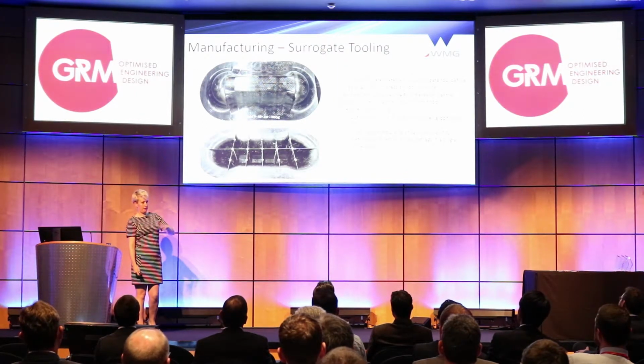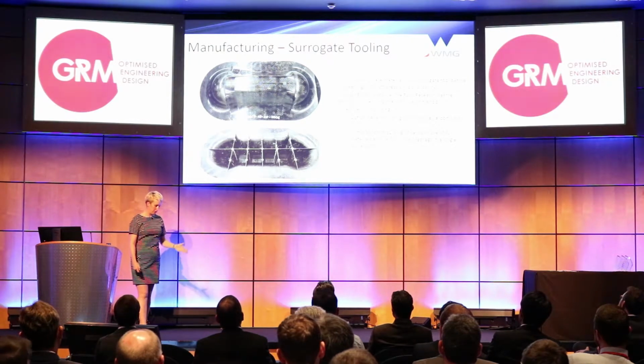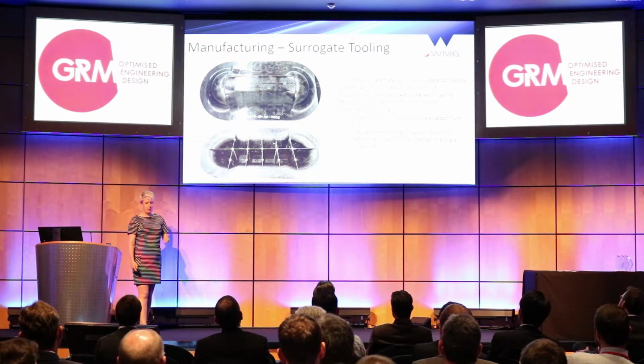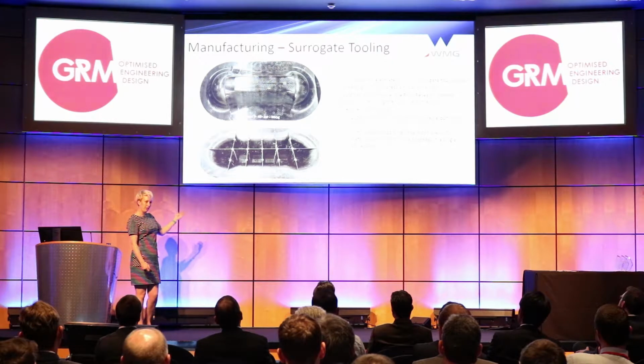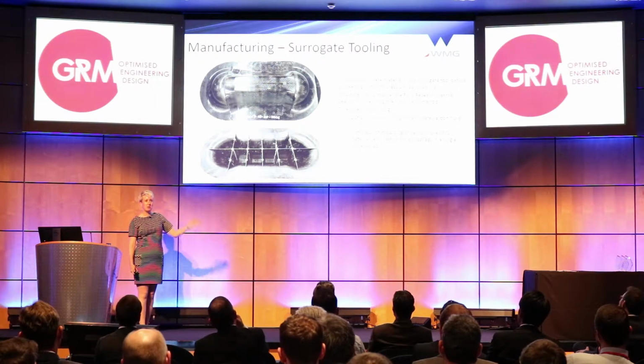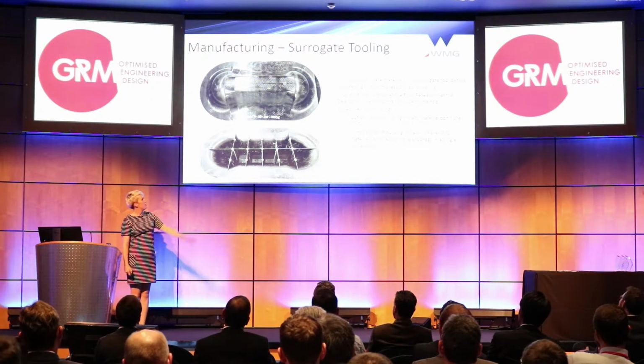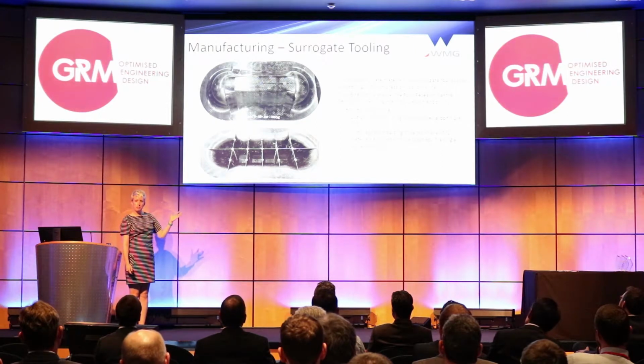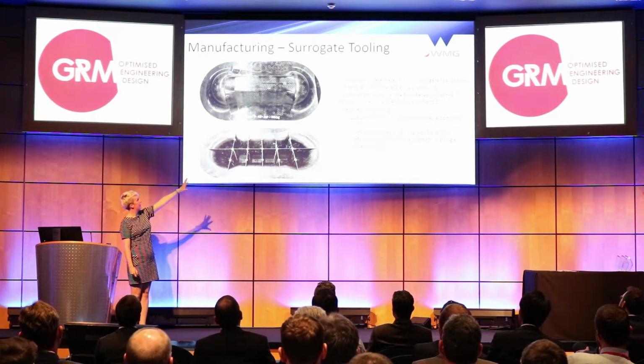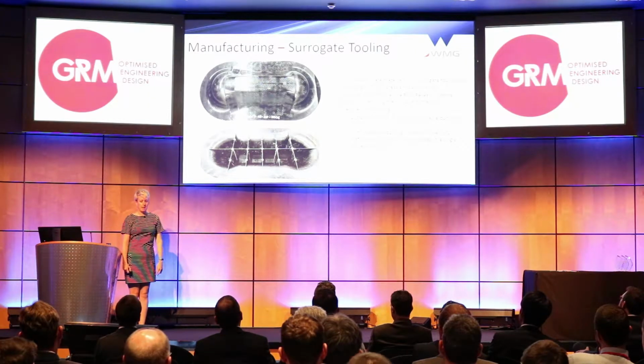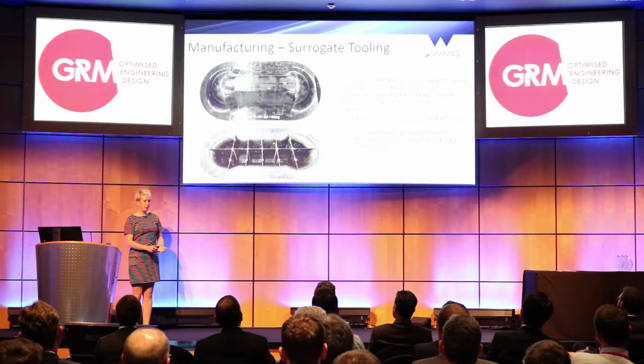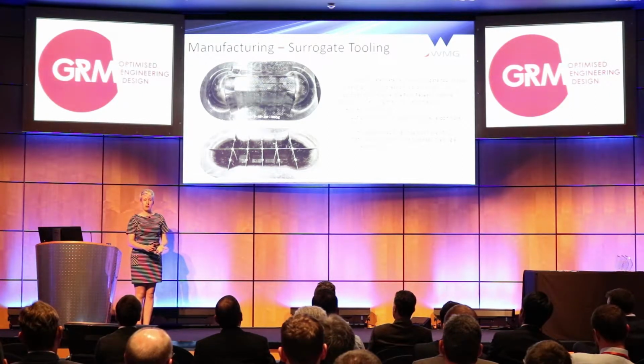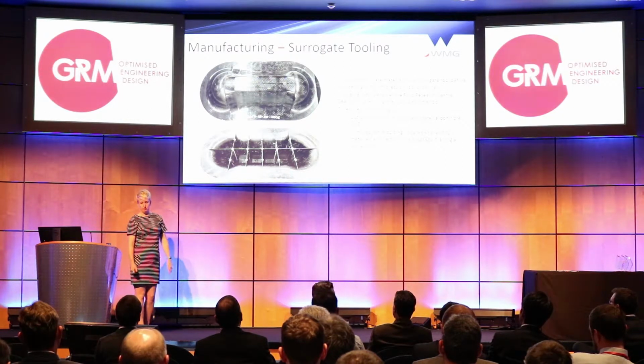So while all that design work was going on with GRM, Ford and Gestamp, we went on holiday to Detroit and made some parts in Ford USA. We used this kind of generic geometry called the double dome. So we had a pre-preg skin and then filled it with SMC ribs. The purpose of this moulding was to understand what happens, firstly, when you combine these two materials in the moulding process, and secondly, what happens when you mould SMC out of plane.